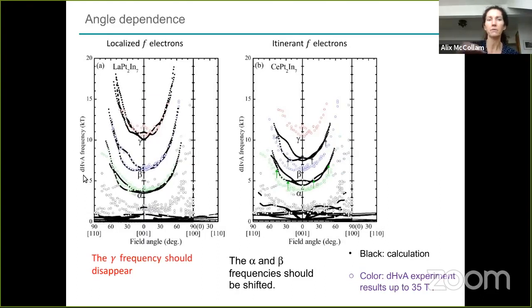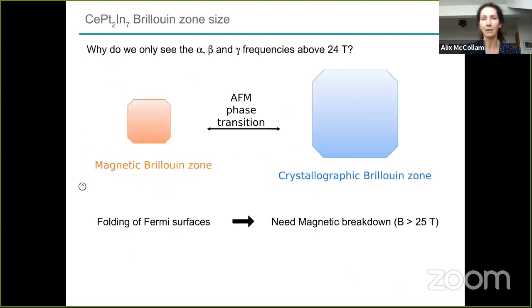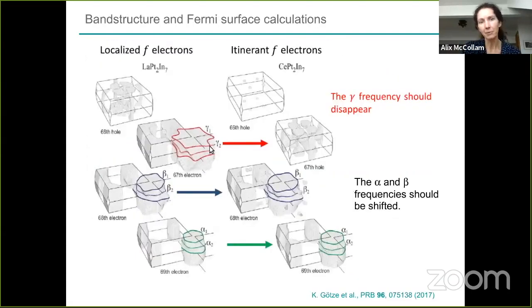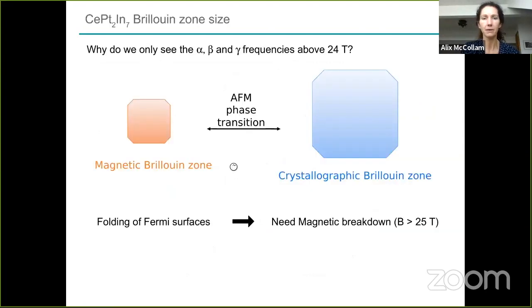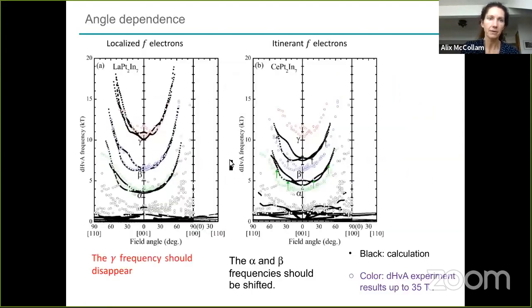So the oscillations that you see, there are multiple frequencies in the curve, and we can separate them using Fourier transforms, as I showed. And the angle dependence gives you basically how, if I go back to the picture, if you measure the angle dependence, your angle dependence is the orientation of the magnetic field. For this orbit, it is pointing in the direction that's straight up and down on this page. But if we tilt this, we get the shape of the Fermi surface as you go all the way around. And so you can get a better idea of the shape of the band structure.